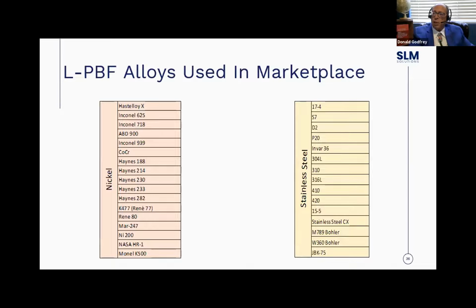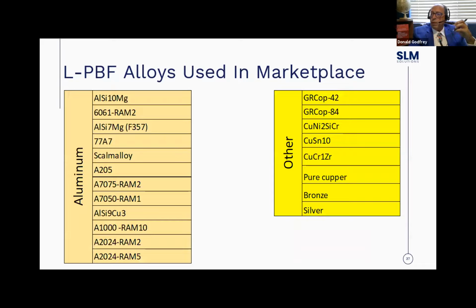Let me go to the next slide. These are the alloys that I believe are most common, and I surveyed multiple companies in the past 6 months across Europe and the United States. Most people are doing 625, 718, cobalt chrome, 939 is picking up, 230, 282. When you look at stainless, the 17-4 is typically in the military and the oil and gas industry, 316. Aluminums, you're seeing a lot of these RAM, 6061 RAM, 7A77. These have great strengths at room temperature, where they fall down, and they're great alloys, they really are.